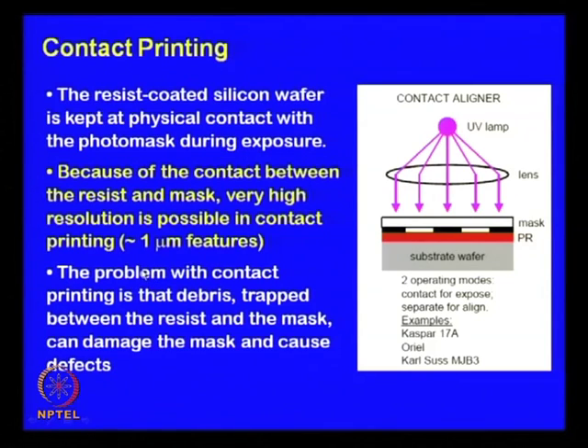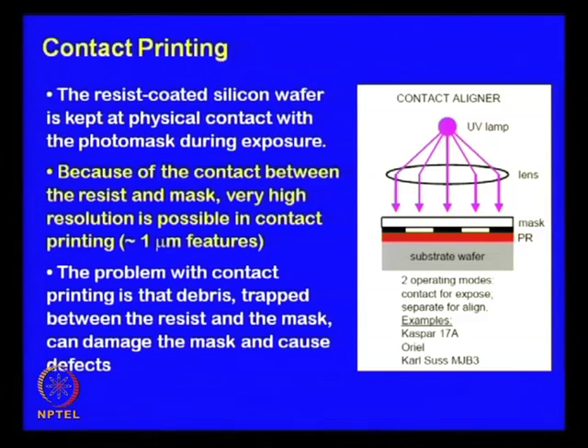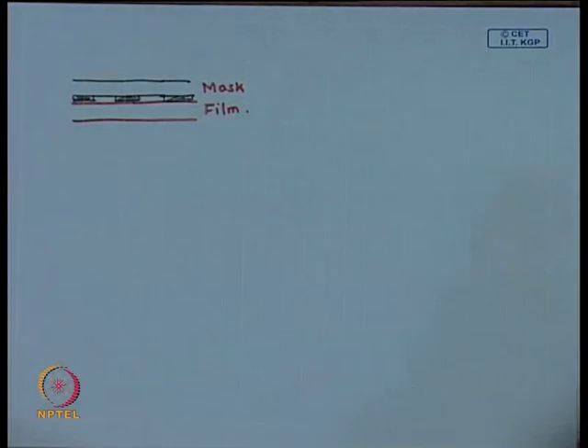Okay. So, as UV shines, you know that there is a structural change of the photoresist polymer layer, which can cross link or disintegrate. Particularly in the cases it disintegrates, there might be some formation of debris, and these debris get trapped. So, where do these debris go? They have no place to go.